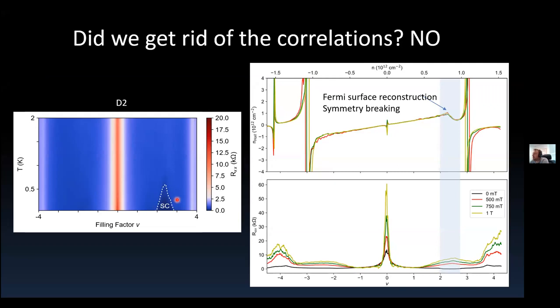And okay, oops, sorry. So for this purpose, you can actually measure the Hall density, and I guess this is maybe the biggest surprise of all, that even in this low angle, even without any significant correlation physics, if you look at this region where we observe superconductivity, first, this color map doesn't do justice, because you still see some broad peak in Rxx that increases with the temperature. But what's even more surprising is that you do see symmetry breaking, or like a blip in this Hall density, which indicates that there is some reconstruction of the Fermi surface.